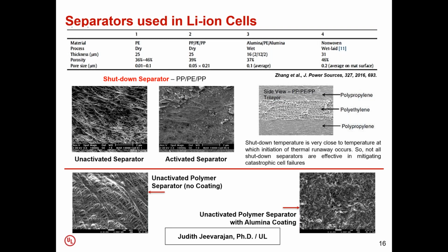More recently, we've seen that the polyethylene separators are coated with an alumina coating. This seems to strengthen the separator. And in some cases, we see that both sides of the separator are coated with alumina, and in some cases, we see that only one side is coated with alumina. And I have some SEM pictures on the bottom to show that, where you can see the weave of the polymer separator in the one that has no coating, and you don't see the weave with the one that has the alumina coating.